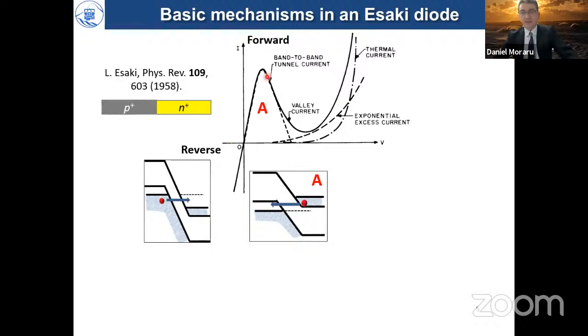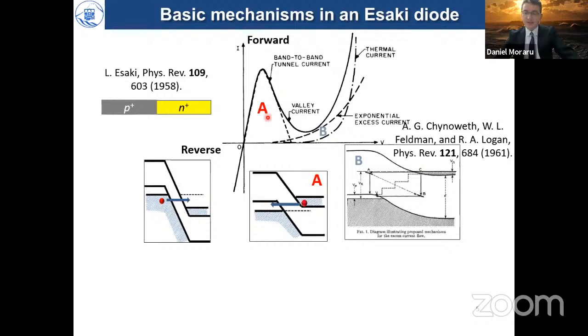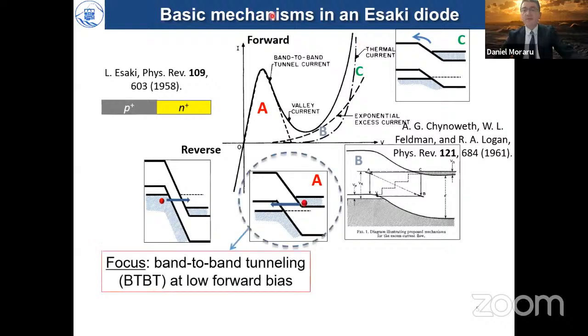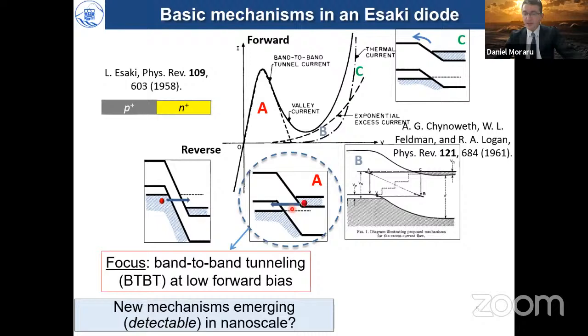It is followed by a kind of an unwanted effect, which is excess current. And this is described by tunneling mediated by some traps or defects in the mid-gap. And it is then followed by thermal current at higher biases, just like a PN diode. So the most important part here is basically the band-to-band tunneling that occurs at low forward bias. And this is where we will focus our attention. Because silicon is also an indirect band gap semiconductor, we might also need phonons, specifically TA and TO phonons, to assist in the momentum conservation in tunneling.